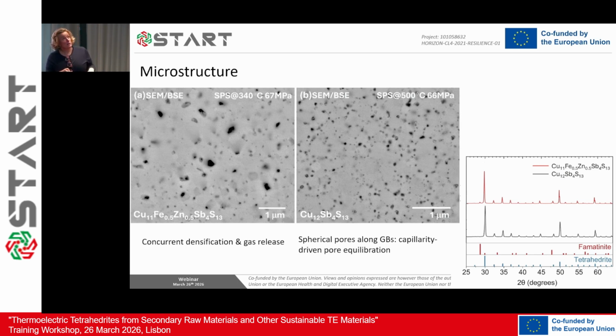When we use low temperatures, what we see is that there seems to be some sort of competition between densification and gas release, because we see a lot of pores and they are quite round. They're not typical of a sintering process that has not finished. They seem much more, especially at higher temperatures, to be the result of capillarity-driven pore equilibration. They're very small and very round, and round always means gas. So we are forming gas.